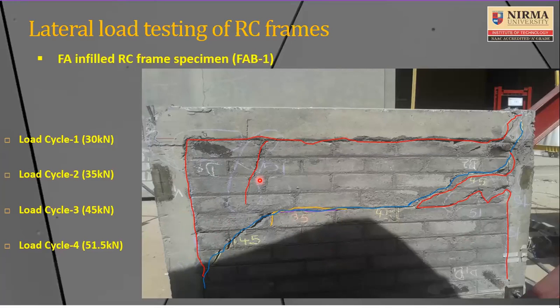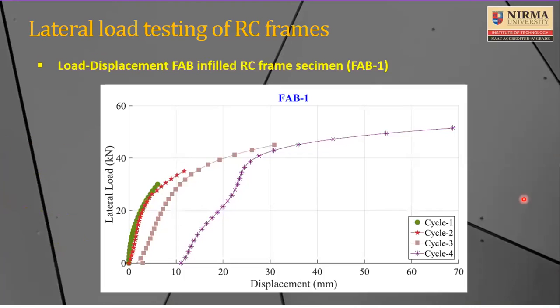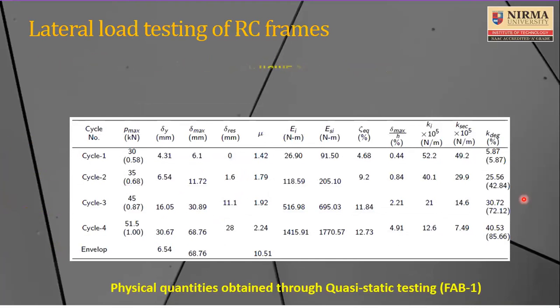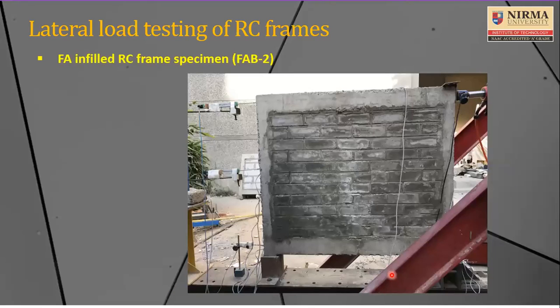In fact, infill attracts a lot of lateral load, and once its capacity gets exhausted, the frame itself starts taking the load, and then that also undergoes damage. So this is the load versus deformation plot, and again you can see it has a very good displacement capacity. The fly ash based test specimen also has a very good displacement capability. Of course it reduced the drift by a large margin, but the stiffness is not as good as the AAC block infill. And the degradation is also huge after a certain amount of lateral load. There is another specimen.